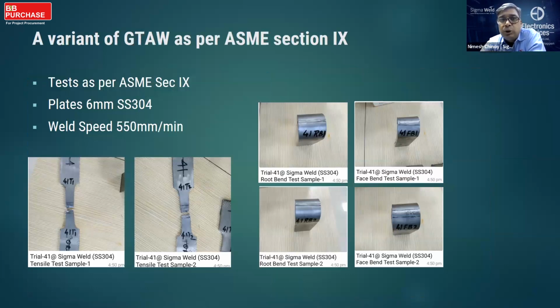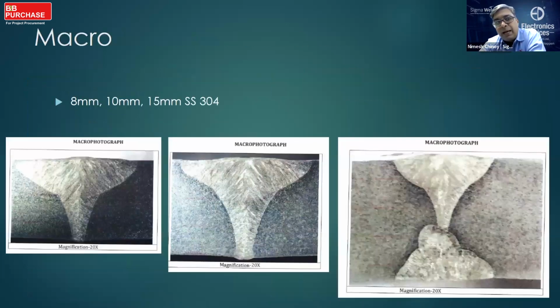The customer has, in the last 3 years, welded more than 22 kilometers of weld length using this process. It's a variant of GTAW, so as per ASME section 9, it has undergone the tests for root bend, face bend, tensile, and it passes all of them, including impact at -196. Here are a few macros, 8 millimeter, 10 millimeters, and 15 millimeters thick. And you can see very clean, clear, exactly what you need.